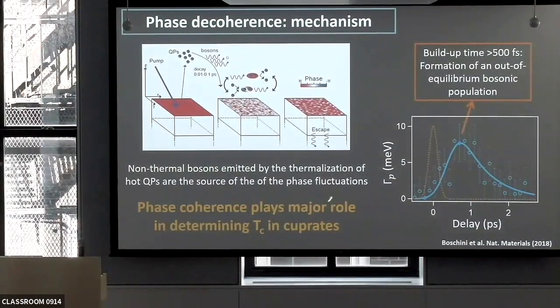So the next part of the work we would like to do is to continue this as a function of doping, as we have talked today about the NCCO. And in particular here, moving towards the overdoped side of the phase diagram. Interesting, if you look at the dynamics, the gamma terms, so the phase rotation terms, build up with a certain delay of half a picosecond as compared to the arrival of the pump itself. So really this is the build-up time of the non-equilibrium bosonic population that you have.